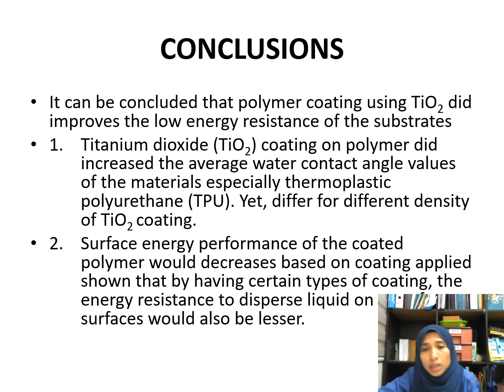As for the conclusion of this study, it can be concluded that polymer coating using titanium dioxide did improve the low energy resistance of the substrate. Titanium dioxide coating on polymer did increase the average water contact angle values of the materials, especially on thermoplastic polyurethane. Yet, it would differ for different density of titanium coating. Surface energy performance of the coated polymer would decrease based on coating applied, showing that by having certain types of coating, the energy resistance to disperse liquid on top of the surface will also be lesser.